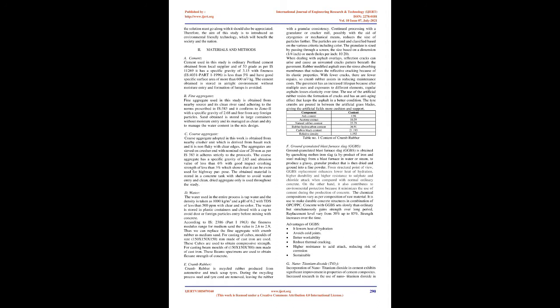and stiffness. Eldin and Senouci, 1993, performed tension and compression tests on two types of cylinders, with portions of the coarse or fine aggregate replaced with rubber. They observed tensile strength decreases of 50% and compressive strength reduction of up to 85%, however noted that the rubberized concrete absorbed a great amount of plastic energy.